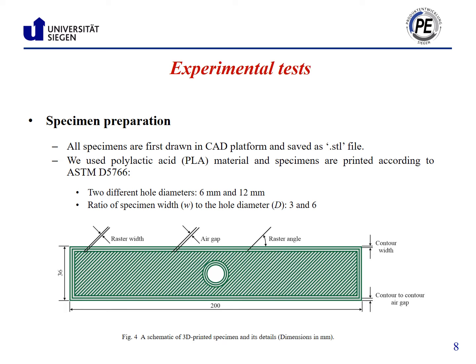In preparation of the specimens, a standard was used and the open-hole plates are printed using the FDM technique. For fabrication of the specimen, at the first step, a CAD file was saved in STL format, and then it was sliced by an appropriate slicing software. Later, the file was used in the 3D printer. In this image, you can see dimensions of the specimen and some FDM process parameters such as air gap, raster direction, and raster width.